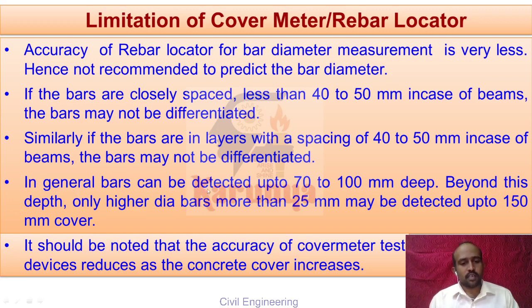In general, bars can be detected up to 70 to 100 mm deep. If cover depth is more than 100 mm, the accuracy of locating rebar is very low. Beyond this depth, only higher diameter bars of 25 mm may be detected up to 150 mm cover. If the cover is more than 150 mm, the device cannot locate the reinforcement. So it should be noted that the accuracy of cover meter test devices reduces as the concrete cover increases.